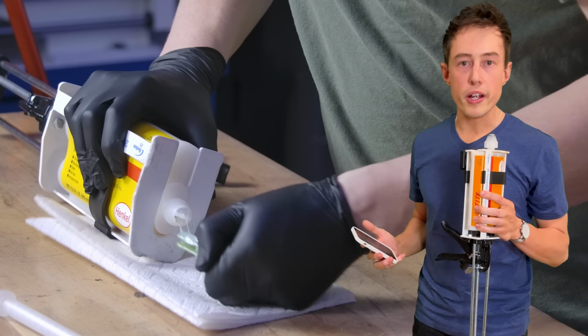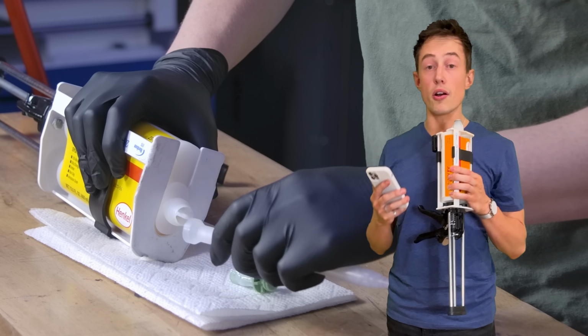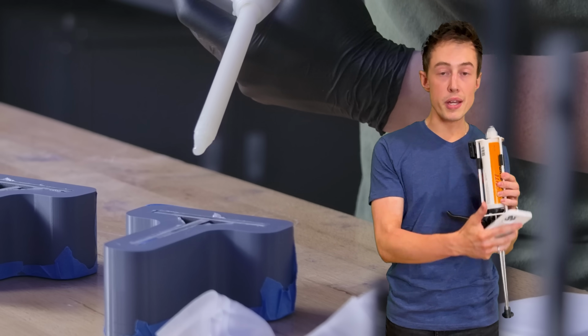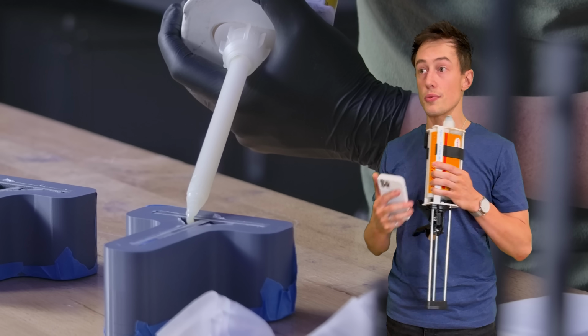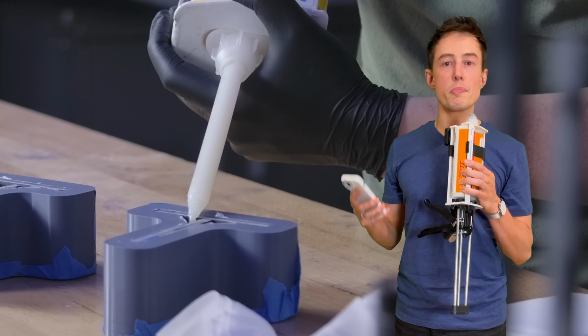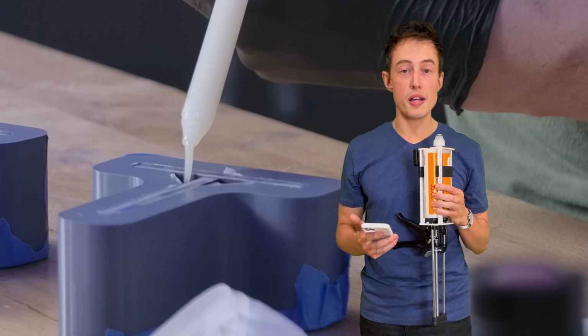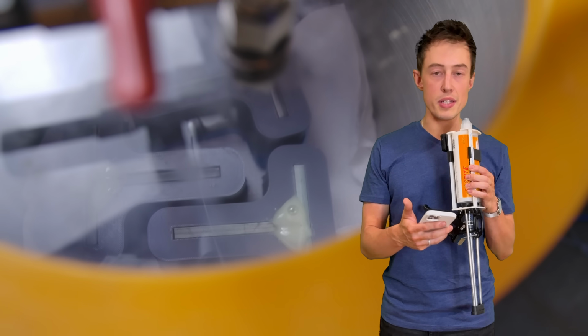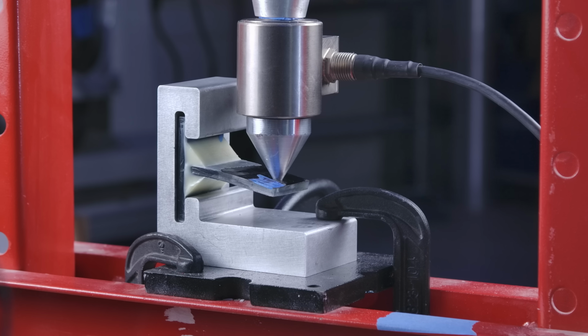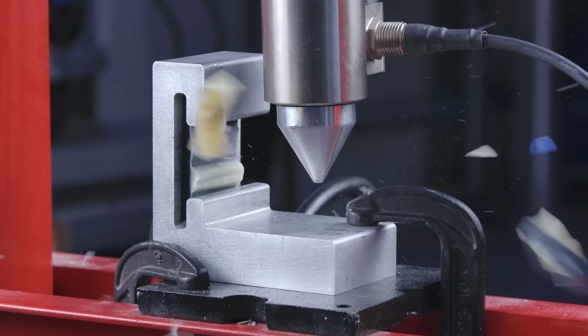To explore every option of getting a stronger bond, I also shortened the time between the epoxy mixing and the bond to the surface to a single-digit number of seconds. I dispensed the epoxy directly through the mix nozzle into the mold, and then I vacuum degassed once it was in the mold. Then I left the mold for 48 hours, knowing I had given this batch every chance that I could at working.